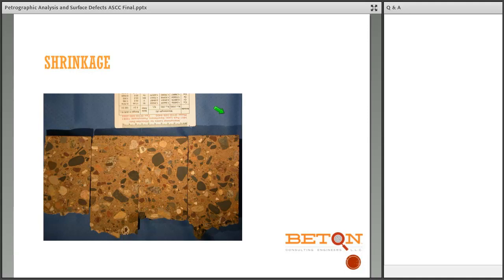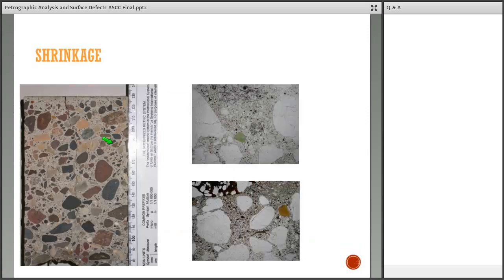Similarly, in this slide, we see a number of cracks throughout the concrete, some of which are passing through the aggregates, which tells us that they occurred after the paste has gained some considerable strength. You can see here the crack passing through the aggregate, and here the crack is passing through the aggregate. These are useful devices to tell us something about the age of the crack, at least the age in terms of the strength gained by the concrete.